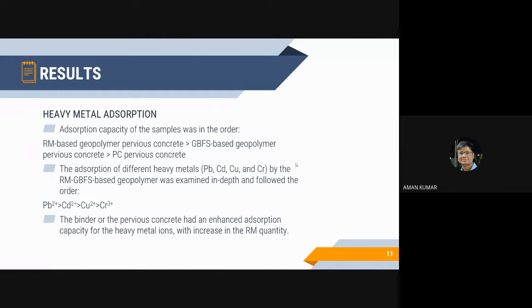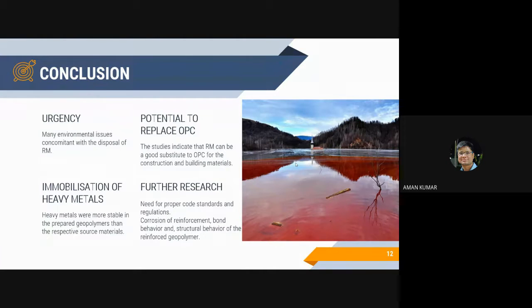To conclude, there is an urgency to find an alternative way to use the pernicious red mud instead of using the conventional way of disposal. The study also indicates that the leaching and heavy metal binding characteristics of geopolymers and alkali activated binders were better than the samples prepared using OPC, thus suggesting that red mud can be a possible substitute for the same. Although, in order to do so, there is a need for regulations and further research is needed on the corrosion of reinforcement, bond behavior, and structural behavior of reinforced geopolymer if it is required for higher strength.